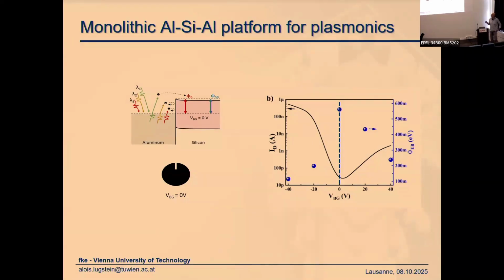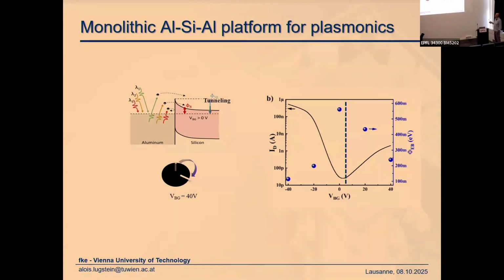Okay, so we can control the barrier height. That means that we can probably also detect light with an energy less than the band gap, because the electrons must only surpass the barrier. So we don't have to excite electron-hole pairs, which is 1.12 eV in silicon. We just have to lower the barrier below the energy of the light that we want to detect. If we change the backgate voltage, we will bend it downwards, and lower energetic electrons can be injected into the channel. That means the barrier changes from 600 meV to about 250 meV.